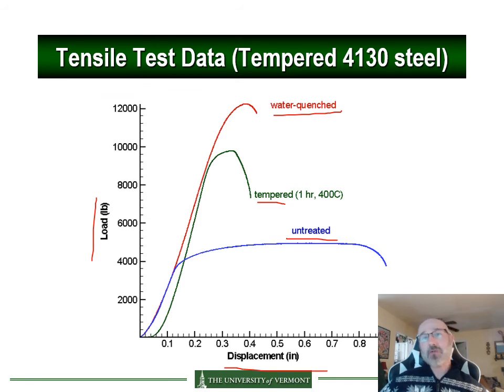So let's talk about the untreated first. We can see this ramps up almost linearly up to here, which is just a little over 0.1 inches and just under 4,000 pounds. It stays pretty much in the linear region there. Then we can see it quickly curves off, and it doesn't break or fail. It just stays there and stretches, and you can see the displacement increases and increases all the way out to almost 0.8, 0.9 inches before it actually fails and the specimen breaks.